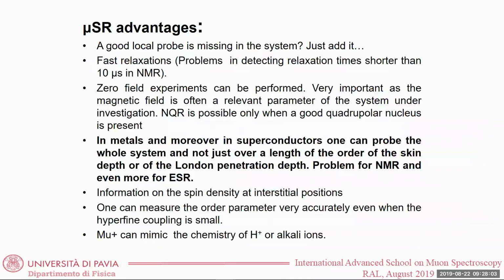Okay, so besides this, there is another good reason that I have already mentioned where MUSR is more convenient than NMR and ESR. And this is the case when you are dealing with metals or with superconductors. The reason is that if you are dealing with a superconductor, for example, the radio frequency field or the microwave field will penetrate just for a depth which is of the order of the lambda penetration depth, which means a few thousand angstroms. In general, it can be a bit more if you have some flux line motion.